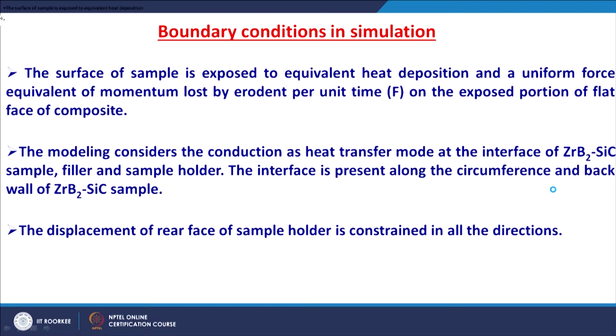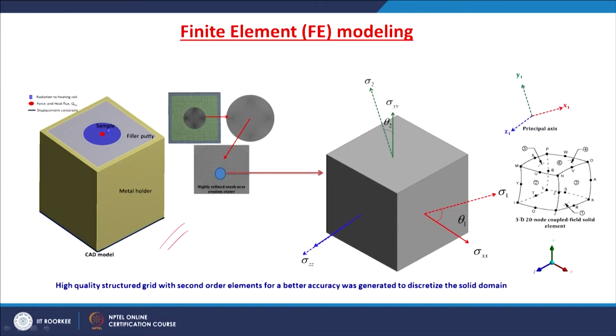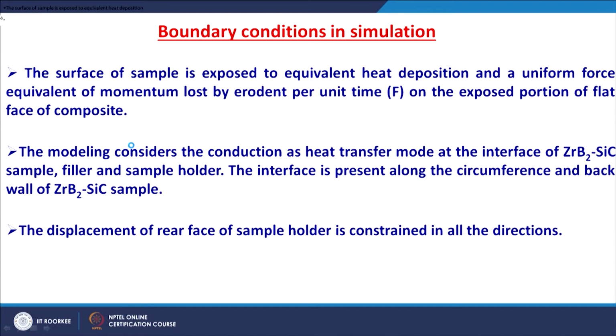In modeling, we considered conduction as the heat transfer mode at the interface of the zirconium diboride silicon carbide sample, filler and sample holder. The filler is used to fix the sample inside this metal sample holder. The interface is present along the circumference and back wall of the zirconium diboride silicon carbide sample. We have the displacement constraints at the back wall and along the walls of the holder. The displacement of the rear face of the sample holder is constrained in all directions.